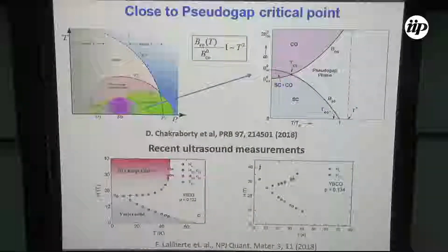So I said earlier that I will be focusing on this part of the phase diagram. Now let's go in this direction, close to the so-called pseudogap quantum critical point. What happens if we plot the phase diagram in the BT plane, we see that the flatness is gone. So it's no longer flat, and the onset field is now dependent on temperature quadratically.